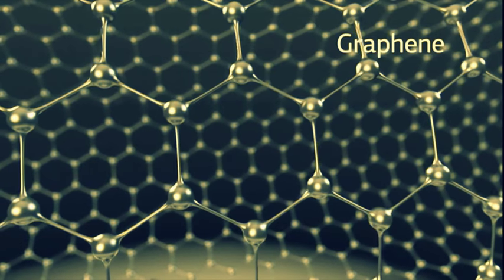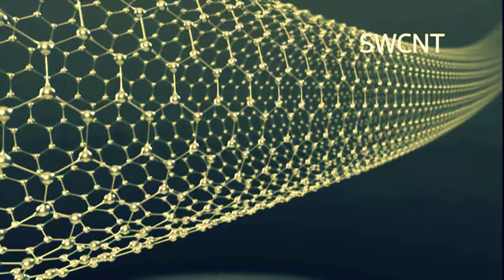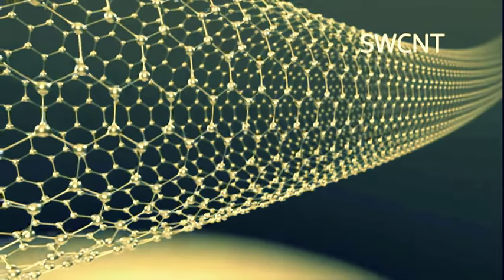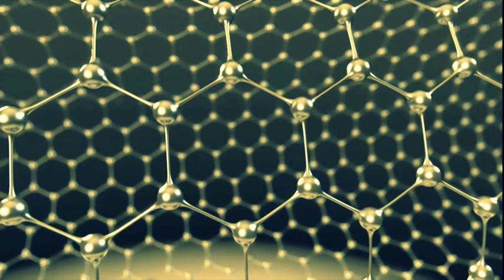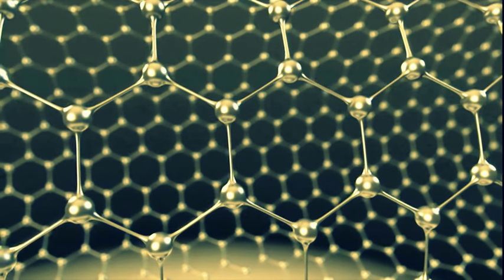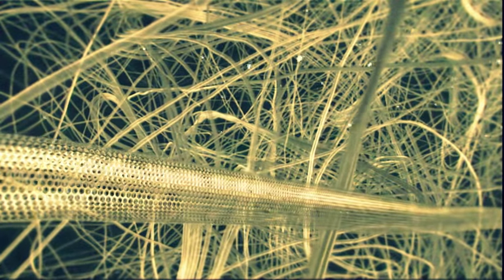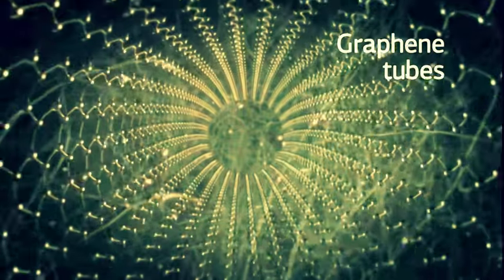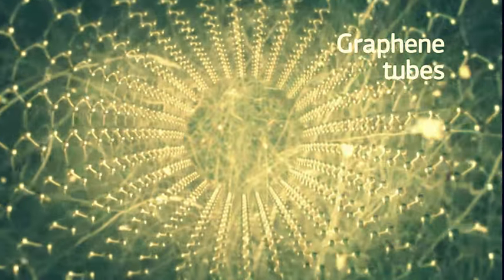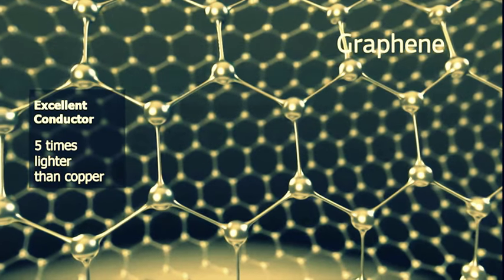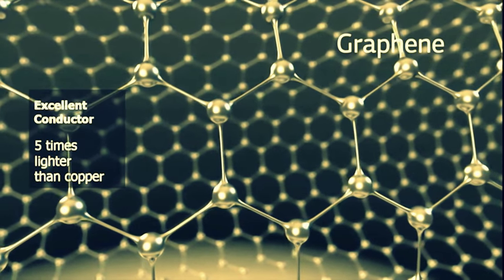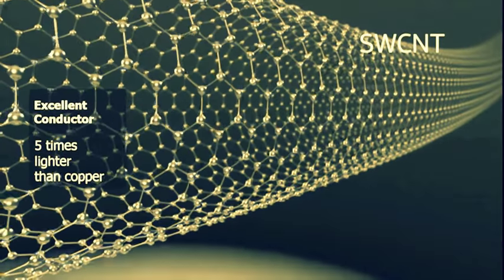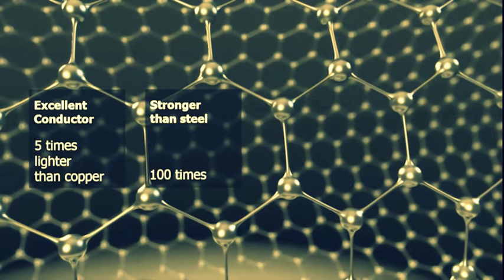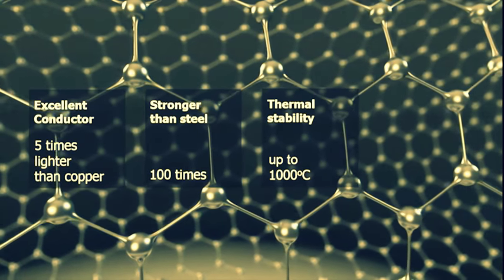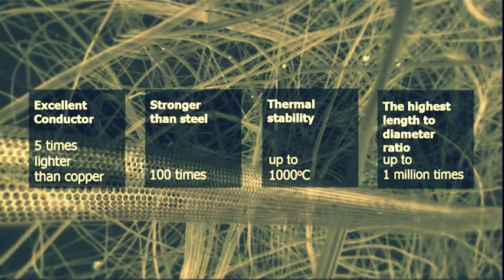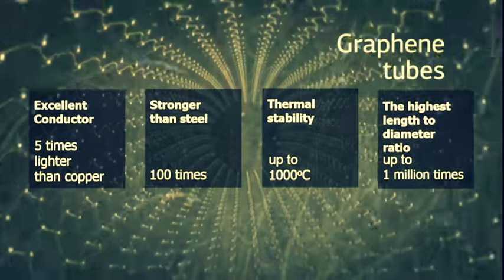So what is single-wall carbon nanotube? It is one atom of carbon bonded with three other atoms in a shape of graphene-like platelet structure. You roll it into a tube, it will be called a single-wall carbon nanotube. You can also call it graphene tubes. Because of its unique structure, they have some exceptional properties. They are excellent conductors. They are 5 times lighter than copper and more conductive than copper. They are stronger than steel in tensile direction, about 100 times. Their thermal stability is extremely high, 1000 degrees Celsius, and they have extremely high aspect ratio, up to 1 million times.